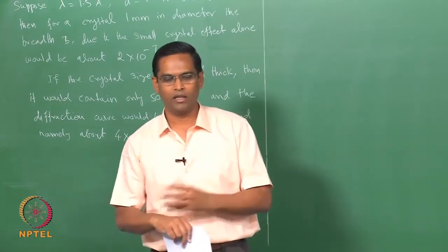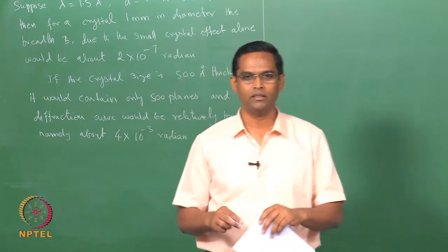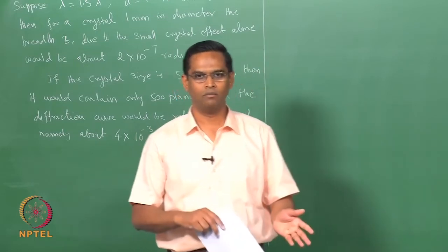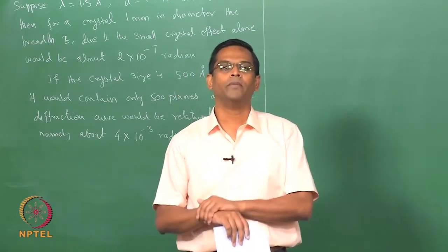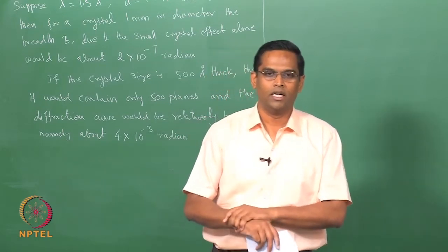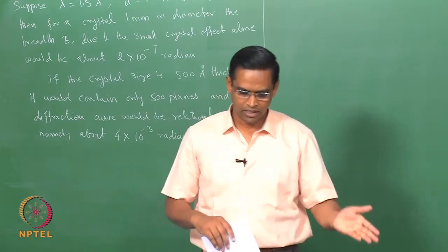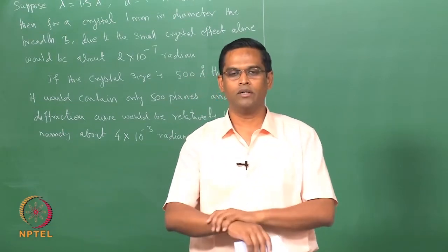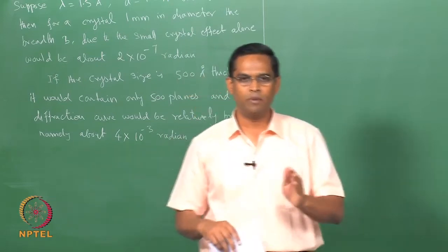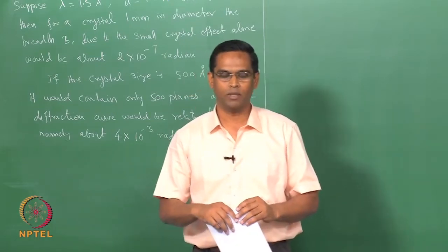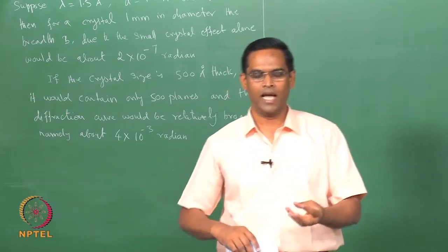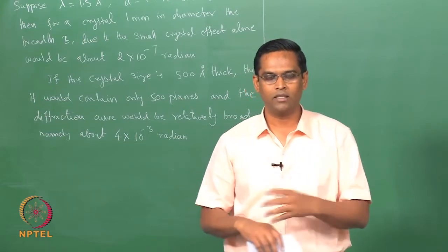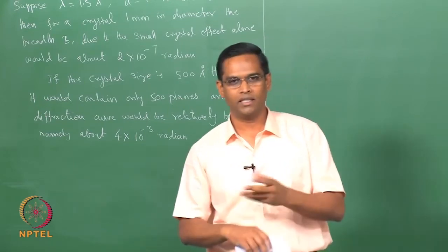So, each grain or single crystal will orient with respect to the neighboring grain with some degree. It could be a low angle boundary or a high angle boundary. So, whatever we just discussed previously about the Bragg theta, here also it will come into effect, because if your neighboring grain is oriented with respect to a given single crystal, even if the angle is extremely small, that orientation is also going to contribute to the X-ray diffraction.